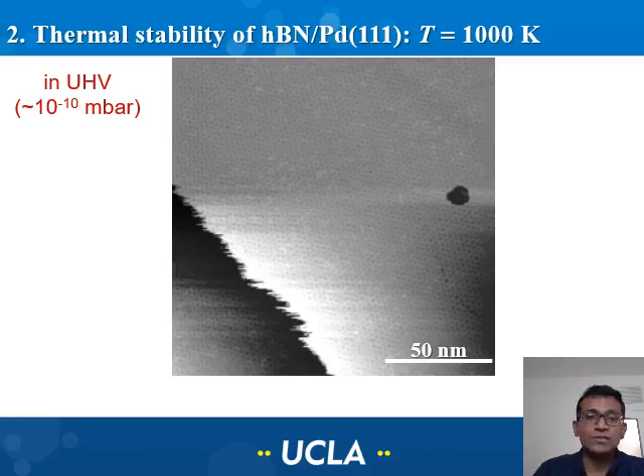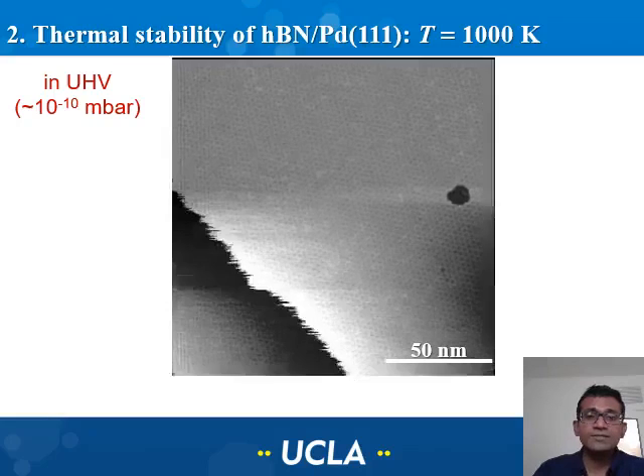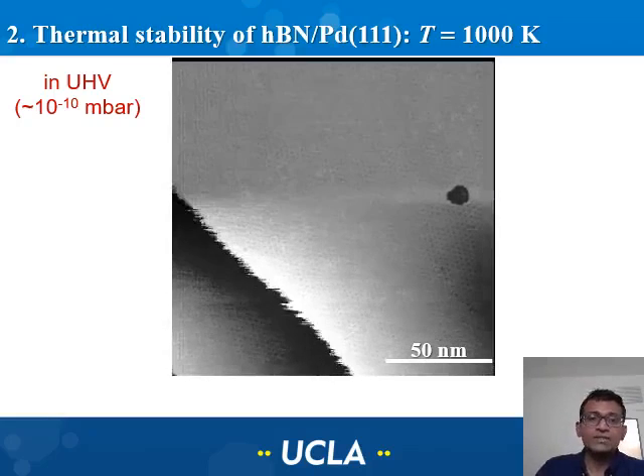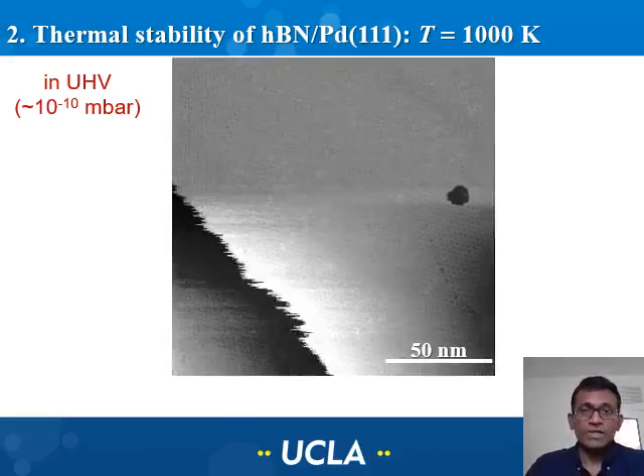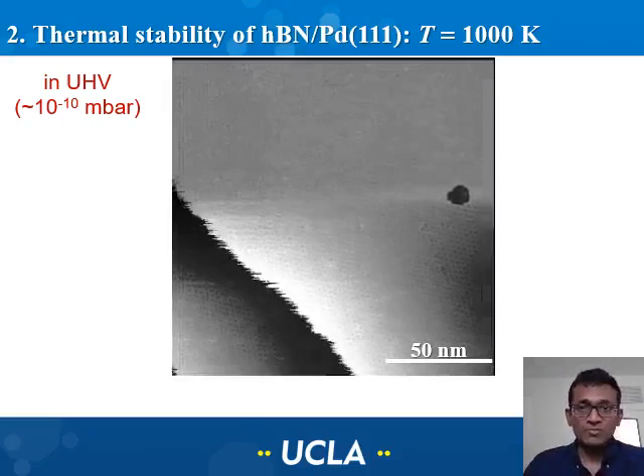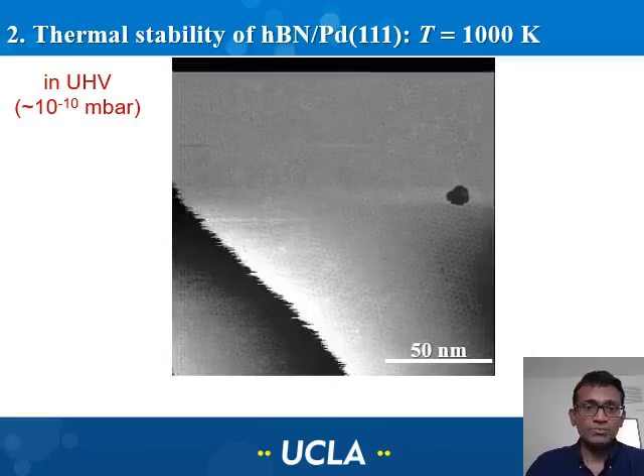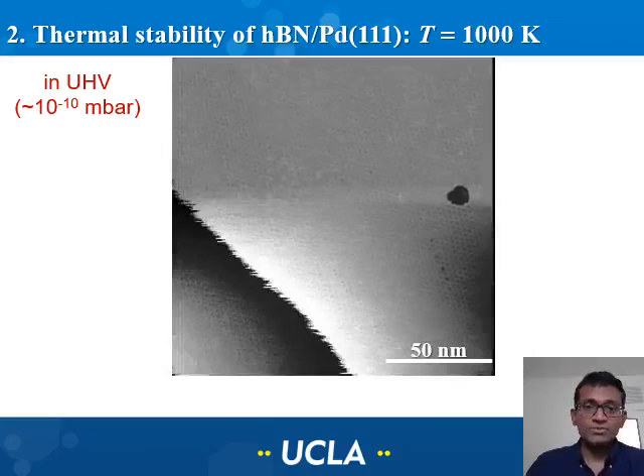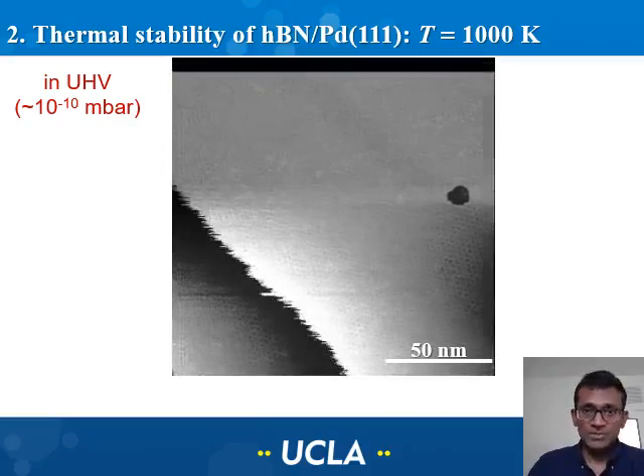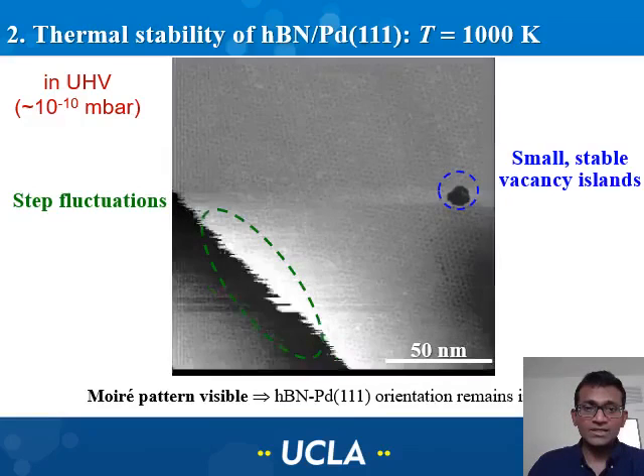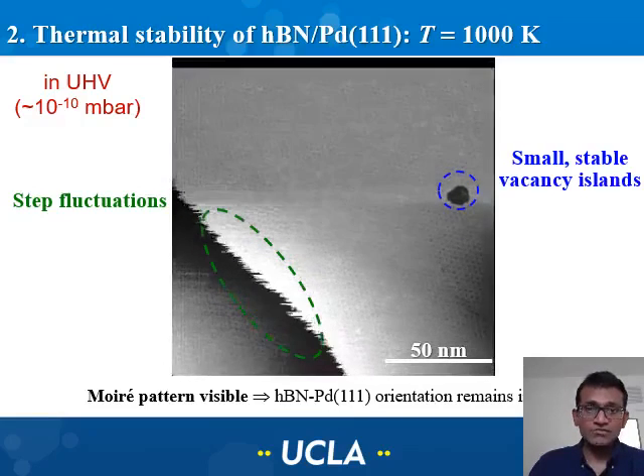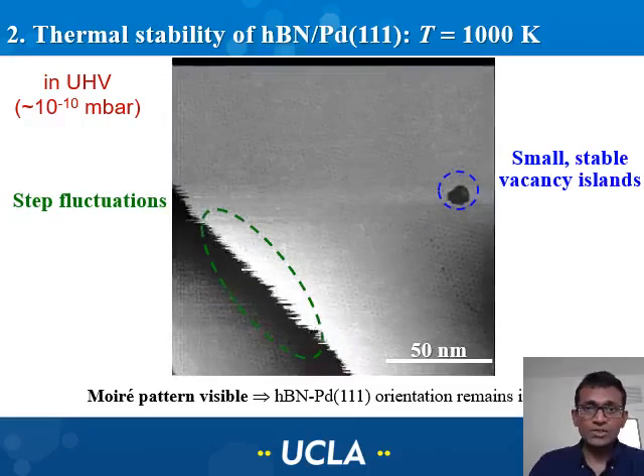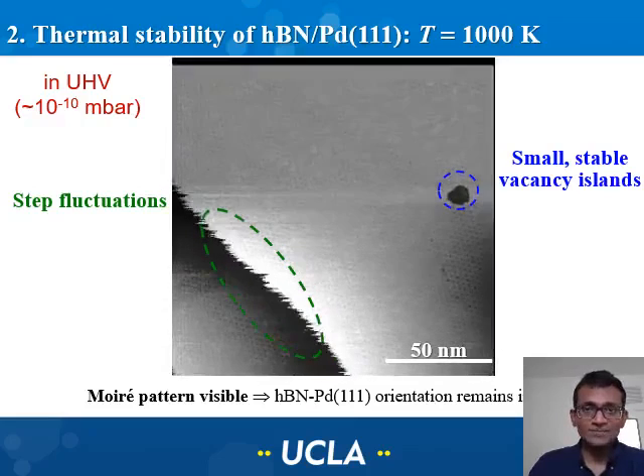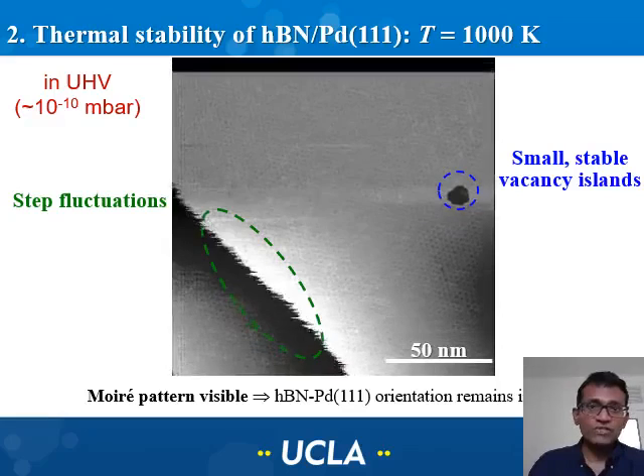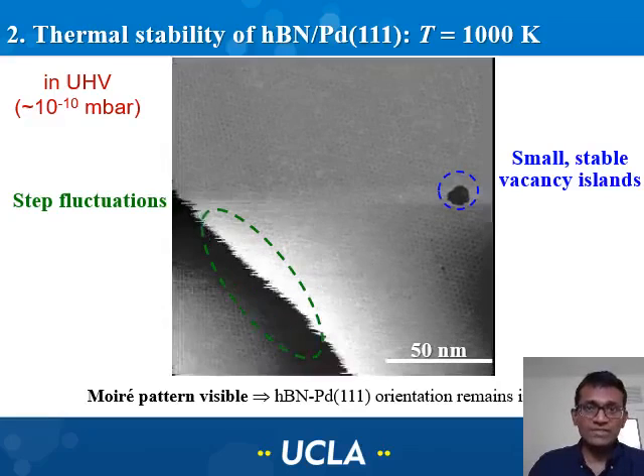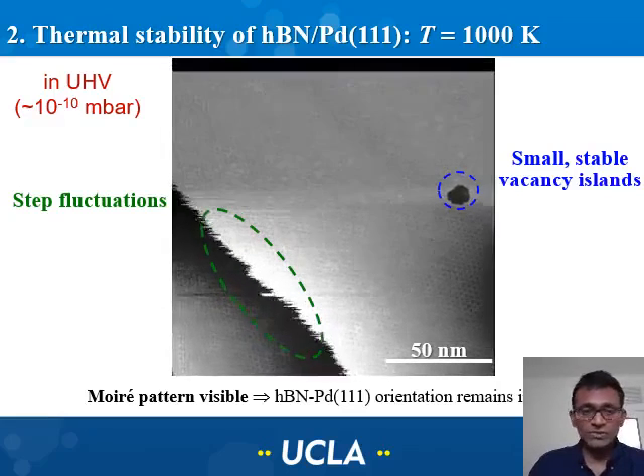and this is because it's a domain boundary between these two domains. Again, these are time-lapse images acquired in the STM while annealing the sample in ultra-high vacuum at 1000 Kelvin. And watch that we do not observe any changes in the moire pattern periodicity, implying that the surface and the hexagonal boron nitride monolayer are intact. If the surface were moving underneath, you would have seen changes in the moire pattern, which we don't.